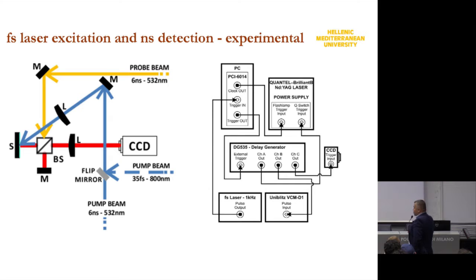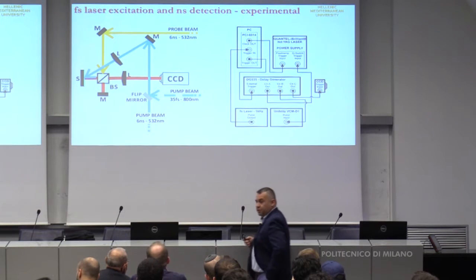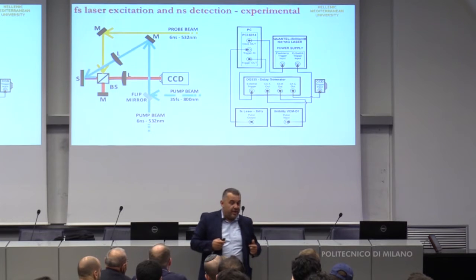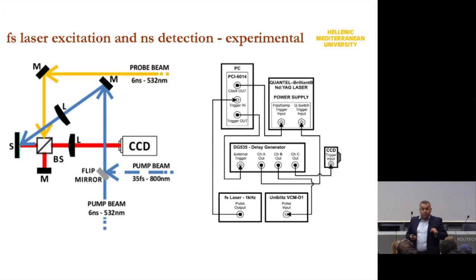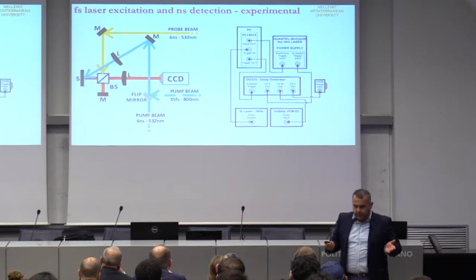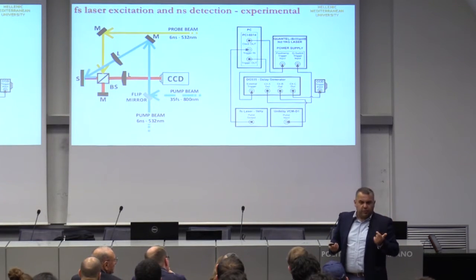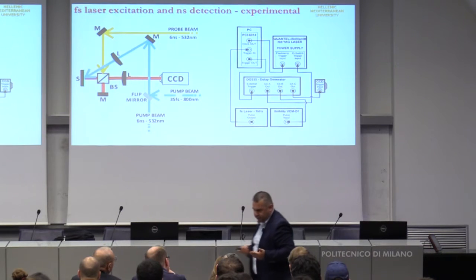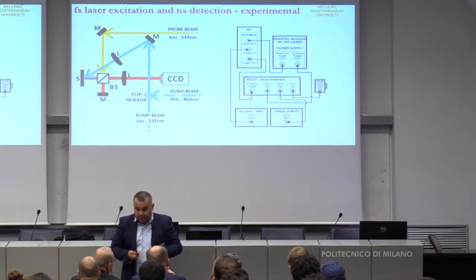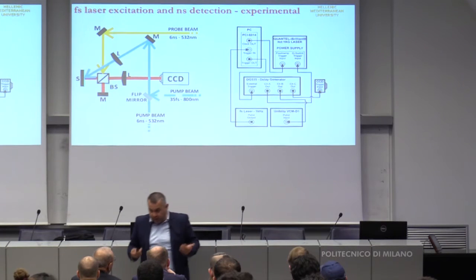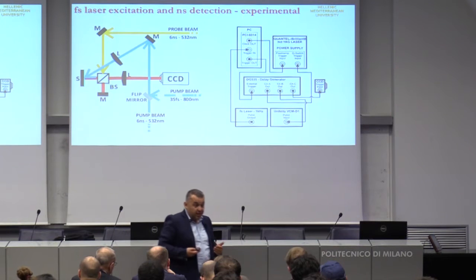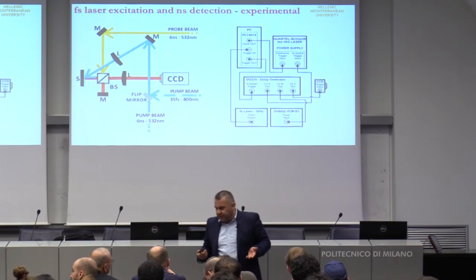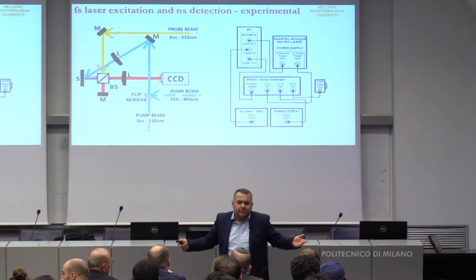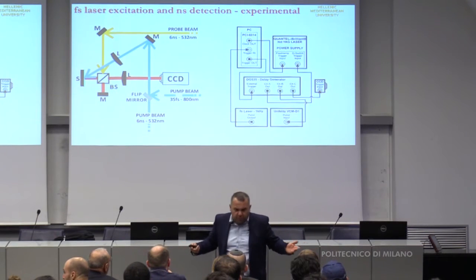And now we are switching to another thing which is more or less similar to the previous, where we have femtosecond excitation and nanosecond single longitudinal mode observation of the surface. Why nanosecond? Nanosecond for two reasons. First of all, single longitudinal mode you cannot have with femtosecond. You cannot have a plane wave with a femtosecond. And for this kind of phase interferograms, we need single longitudinal mode. The second reason is that the speed of sound of the Rayleigh waves on the surface is very, very slow. Nanosecond is more than enough in order to observe them.